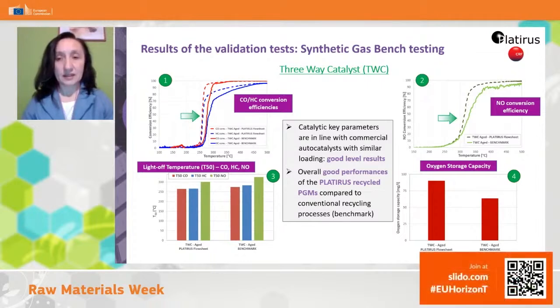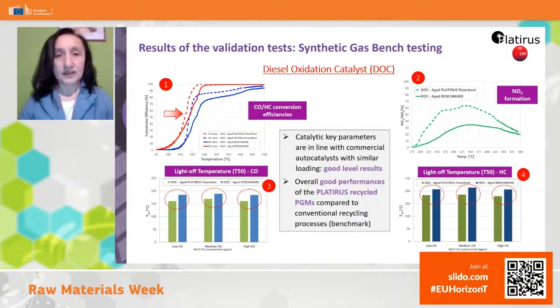And so also in this case, you can see that the PLATIRUS flowsheet PGMs recycled has the best performance. Next slide, please. Okay, here you have the same key parameters for the diesel oxidation catalyst. Also in this case, you have the conversion efficiency in graph 1 for the carbon monoxide and the hydrocarbons. And in graph 2, you have another important key parameter, that is the nitrogen dioxide formation. That is important because it's the ability of the DOC to produce the NO2 that could be available for the